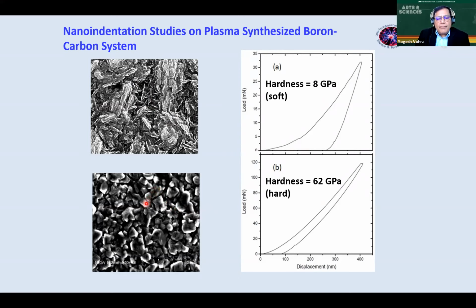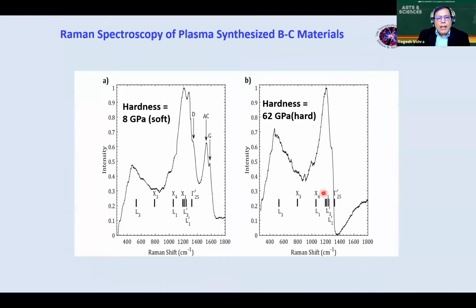The second was a material which has hardness of about 62 gigapascals. And the Raman spectrum, of course, indicated the multiple structure like was predicted by theory. It agrees quite well with theory. And the soft material has some graphitic peaks in it, which may be the graphite doped with boron, actually.